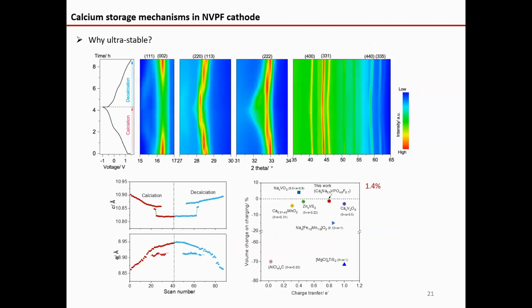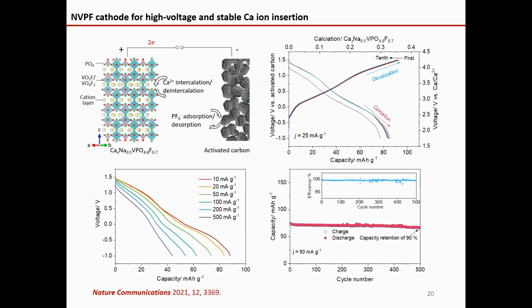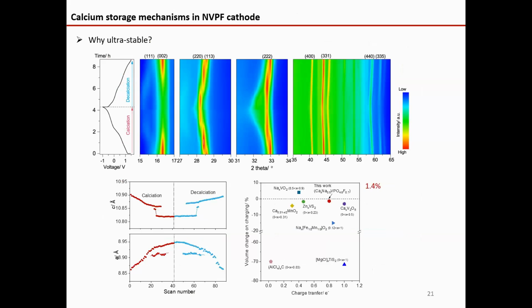Now, why is it so stable? We conducted the in situ XRD and calculated the lattice parameter change. We found that the structure change is very, very small. It's only 1.4%. So such a low volume change during the insertion and extraction of ion can maintain the host stability.